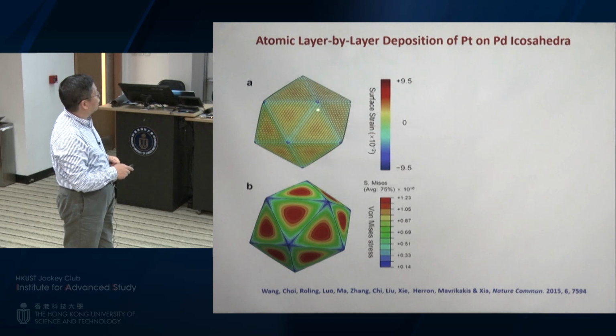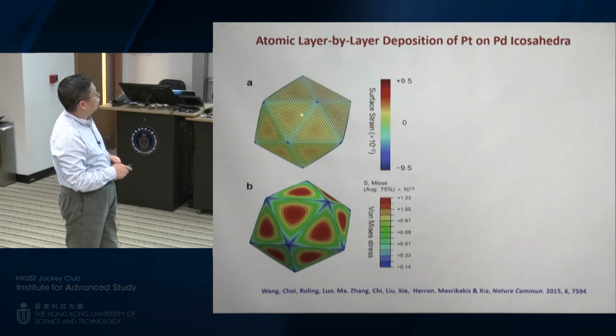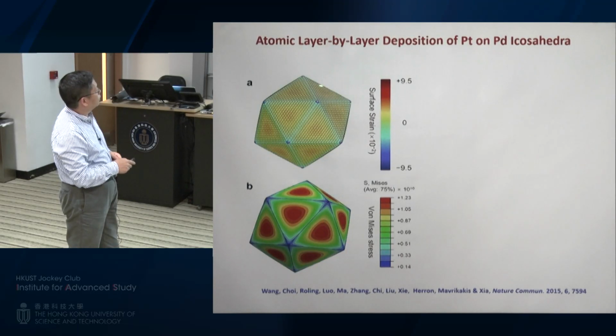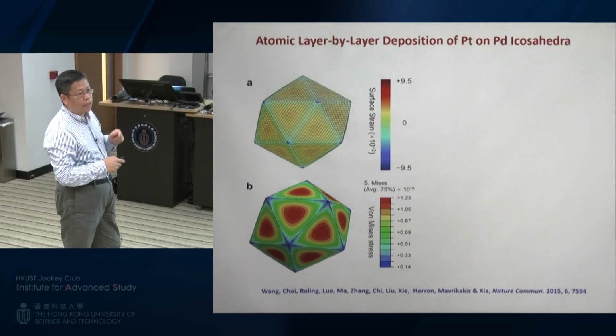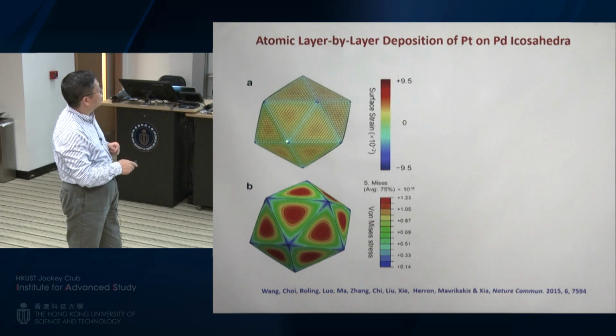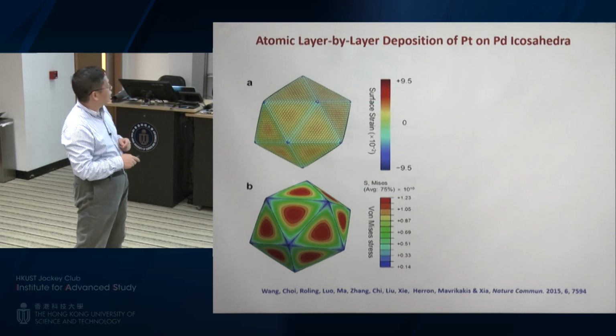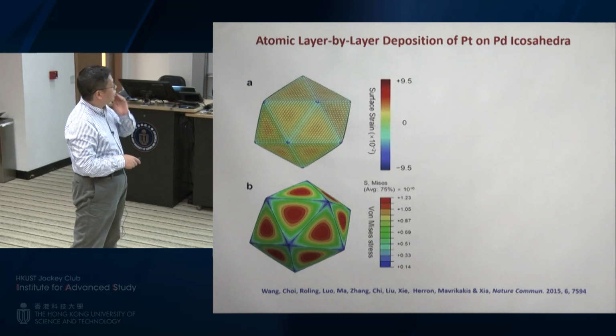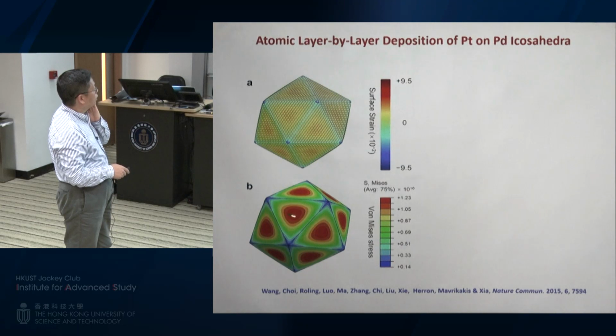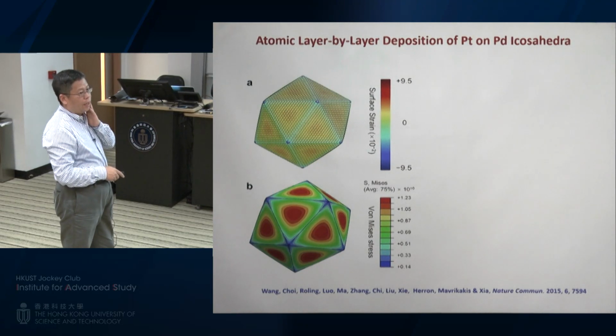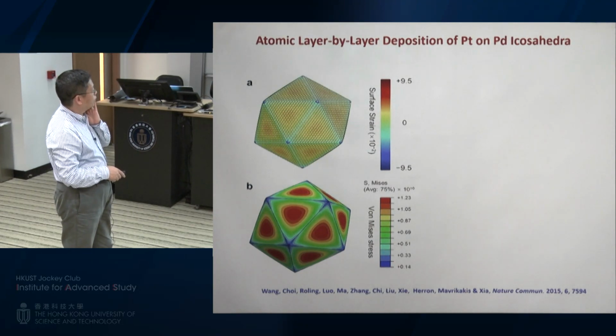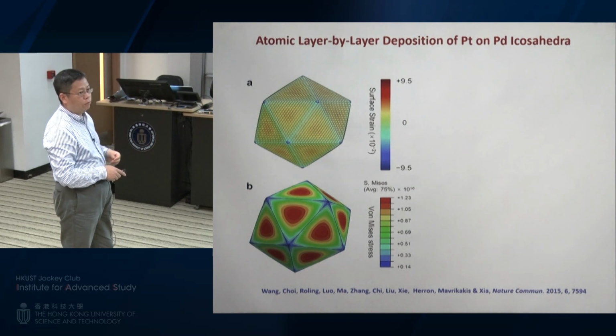So that's based on the icosahedron. The icosahedron is related to the octahedron because the surface is also 1-1-1. But at the same time, you're going to have some twin boundaries. You have 20 twin boundaries between these different facets. And these twin boundaries will eventually induce strain on the surface. And for ORR and other reactions, these strains can further enhance activity compared to